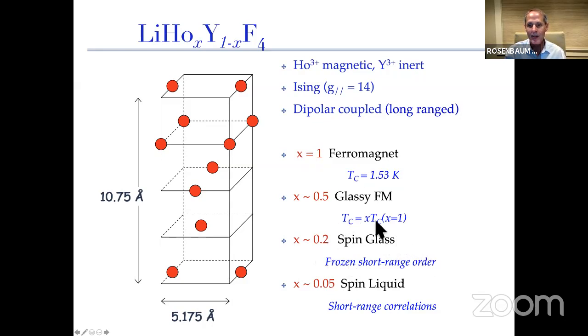If you go farther down, then the sufficient disorder and the competition between the bonds gives you a spin glass state. And when you go even more dilute, you get into a state where you have short range correlations, but no ordering. And I'm going to spend this evening talking about the glassy ferromagnet, that's the magnetization measurement, and then the spin liquid, which is the measurement which talks about disparate spin clusters that can encode information.